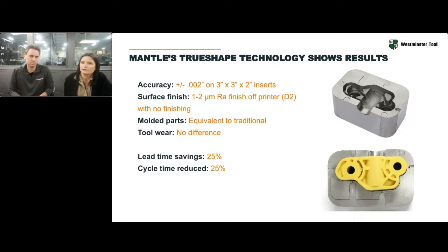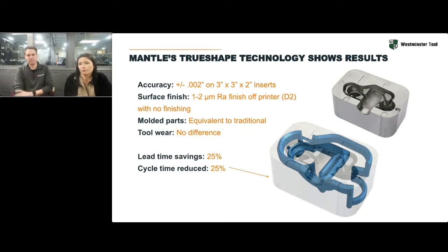When we molded it, there was no change. The quality was on par. We did square up the block, machine in primary vents, put in ejector pin holes, and burn in a subgate, but we didn't touch part geometry. Most importantly, we were able to do that 25% faster than when we had made this same component traditionally. And here are the conformal cooling lines that we had put in it. This part in particular was a huge influence in reducing cycle time by 25%. We also had some parts where the gate was burning and causing quality defects that we were able to address with this as well.